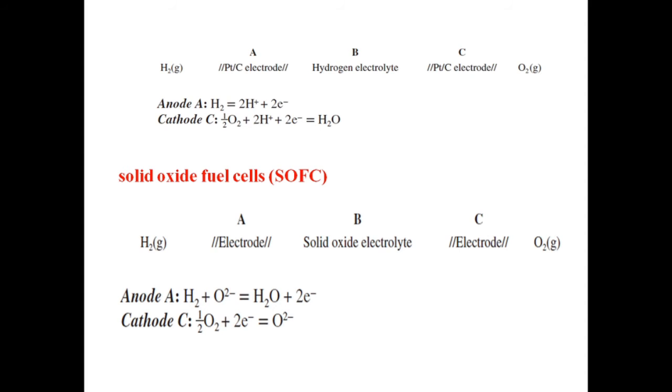The electrolyte becomes O2- conducting at a very high temperature, 800 to 1000 degrees Celsius. This system has the disadvantage of needing energy to heat the cell, but the advantage that at this temperature reforming and H2 production can take place internally without the need for expensive platinum catalyst. Because of the long time needed to get the cell up to its operating temperature, it is not useful for powering vehicles, but it can be used for power generation in buildings and industry.